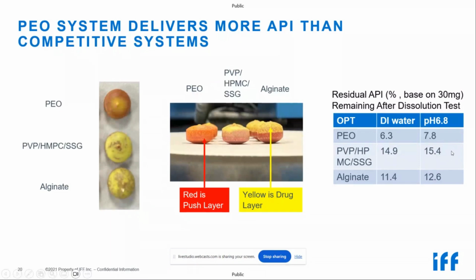Quantifying the amount of drug that remains, we see that PEO has anywhere from around 6 to 8%, depending on a little bit of difference in the pH environment, but not by much. And the PVP, HPMC, and SSG, and alginate had almost double the amount of drug remaining in the system, around 12 to 16%. So PEO systems are possibly more efficient in getting out drug in an osmotic pump tablet than other polymer systems.